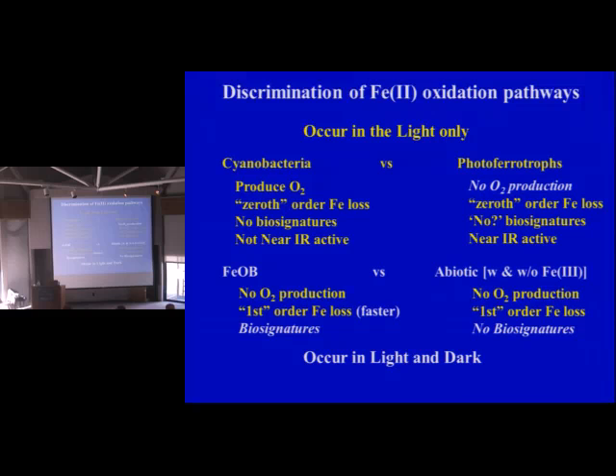Iron 2 does react with manganese dioxide relatively quickly. Dick Postma published this about 20 plus years ago, and he saw iron 3 precipitates and manganese 2. So the question then is, which is first, the iron oxidation or the manganese? Well, it turns out, to have oxidation to MnO2, you would have to have a high pH if it were chemical, or you have to have microorganisms.